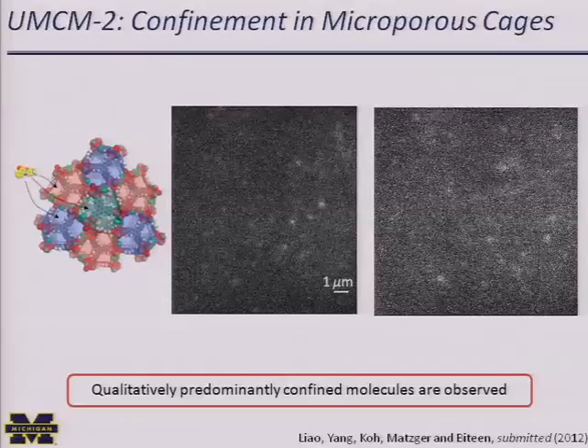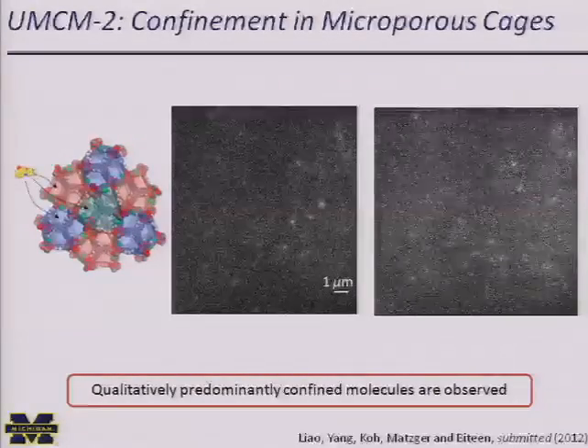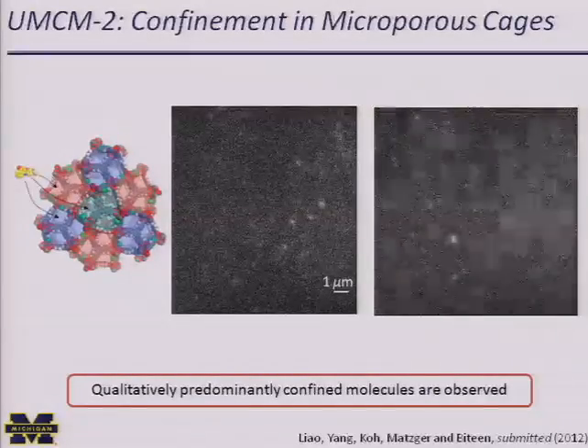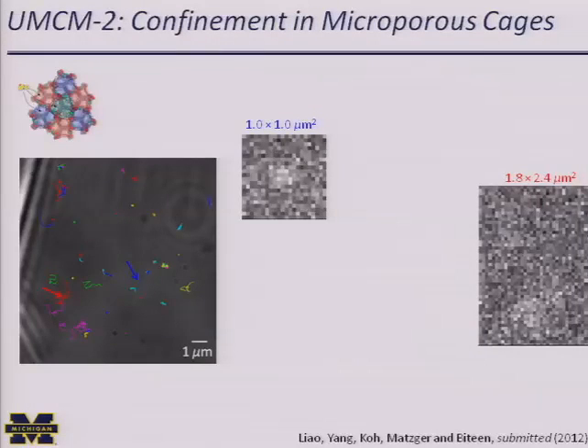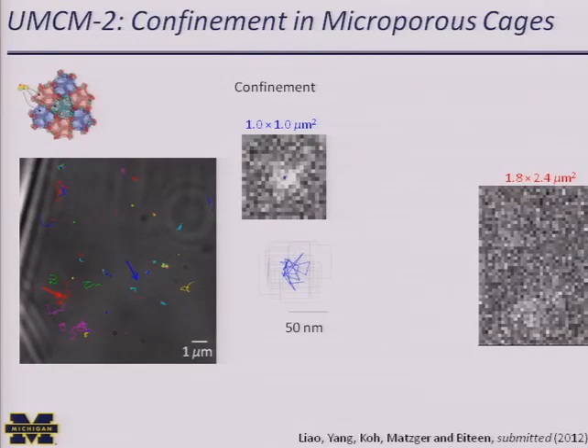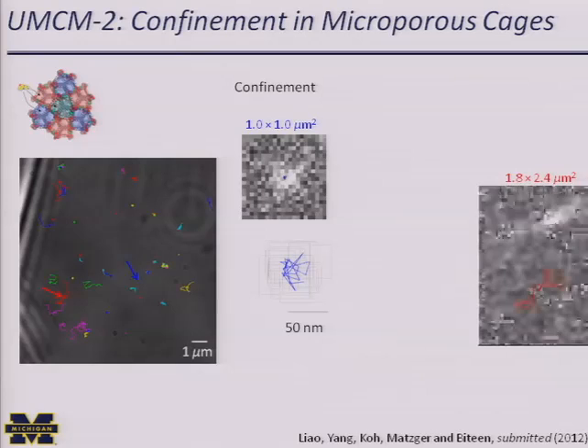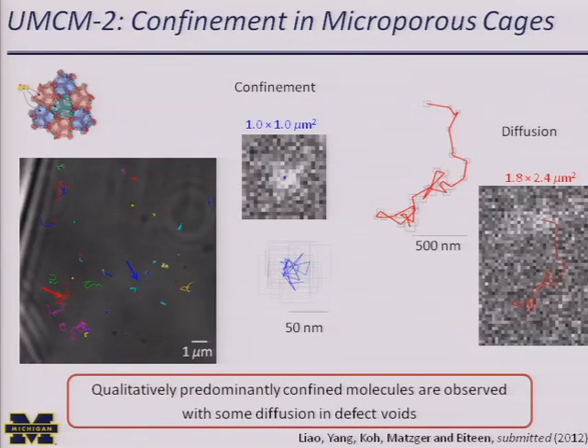So we see this movie where every molecule we see is trapped except a few, and there was one running around there. So we can track them now, and so if we look at this blue molecule, it's tiny, it barely shows up. This is what we generally see, these very highly confined tracks. However, this red track over there, that was one that probably jumped out in your eye previously, is moving a lot. And so that seems to be diffusion in a defect void. And so single molecules can actually show us something about the proportion of defect voids.